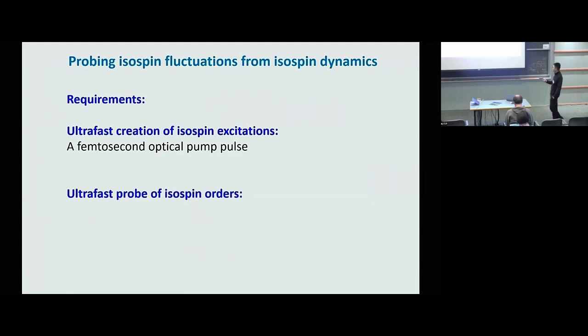So how do we probe isospin orders at ultra-fast time scale? Well, one of the main problems here is that these isospin orders are at quite low energy scale, typically sub-milli eV. So if you convert to frequency, that's 100 gigahertz or sub-terahertz. So it looks like we have to use some terahertz light or 100 gigahertz light, which is very hard to work with. But even in that case, it is still unclear how this terahertz light would couple to these isospin orders to probe them.